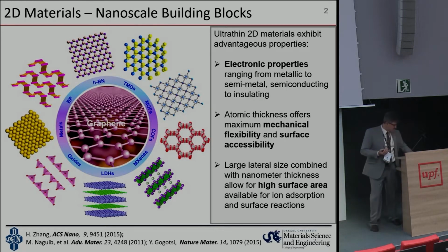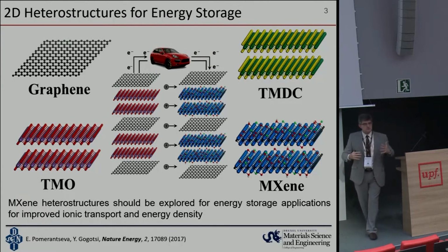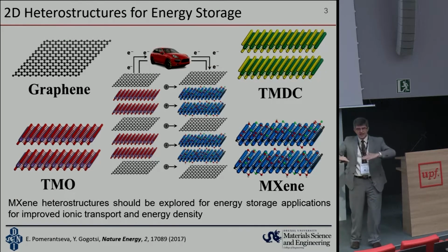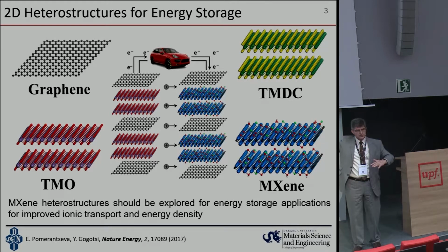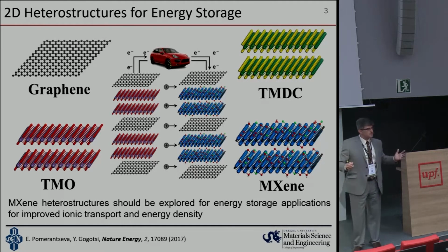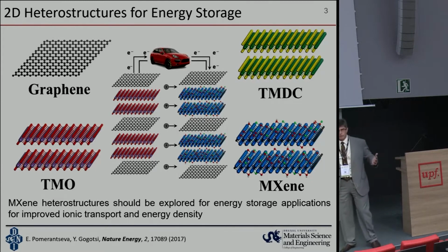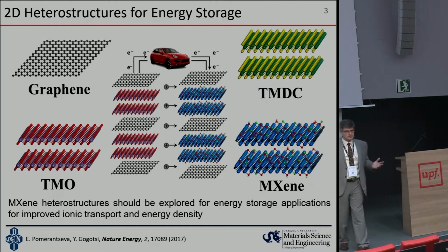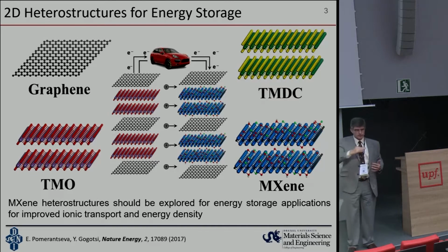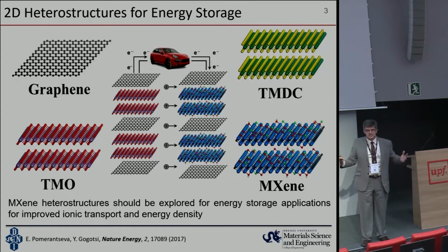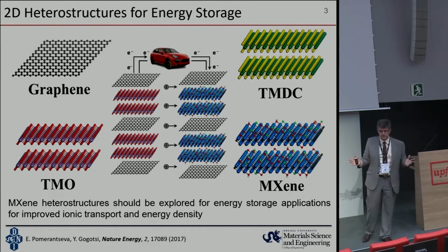But even more exciting, what is great about the 2D state? You can pile up any kind of flakes. You can combine them in any order. You can make a metallic layer, a current collector. You can make another active material layer. You can make a separator, which is dielectric flakes. And you can build it by the same method, whether deposition from solution, spray coating, or anything else. So we basically have an opportunity to create hybrid materials, built from bricks which are a few atoms thin, or even sometimes a monolayer of atoms thin, creating an entirely new generation of artificial material.